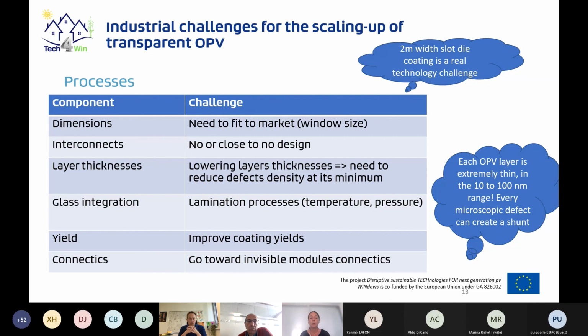The transparency of the layers is also related to their thicknesses. So for transparent OPV we need to lower the layer thicknesses. And related to that, we really have to reduce the defect density. Just as a reminder, each layer in OPV devices is really thin, in the range between 10 and 100 nanometers. So every time we have a microscopic defect on one of the layers, we can create a shunt and then have issues with performance, lifetime, or the safety of the product; if we have some burns, that can be a real issue. Meaning that we really need a coating capacity with no defects to have the possibility to decrease each of the layers of the devices in a safe way.